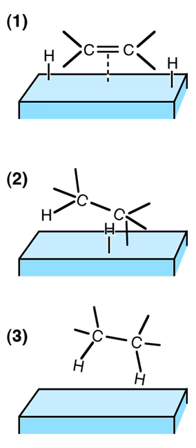Platinum, palladium, rhodium, and ruthenium form highly active catalysts, which operate at lower temperatures and lower pressures of H2. Non-precious metal catalysts, especially those based on nickel such as Raney nickel and Urushibara nickel, have also been developed as economical alternatives, but they are often slower or require higher temperatures.